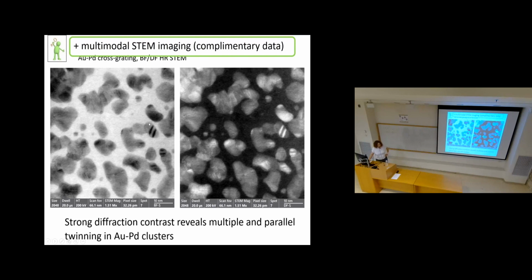And this story could be done even with atomic resolution, but currently what is interesting is that we have complementary data. So we can distinguish between, say, multiple twinning and parallel twinning here. And here we have mostly diffraction contrast and less mass thickness and less Z contrast, because the acceptance angle of these detectors was tuned to the diffraction angles by the gold lattice.